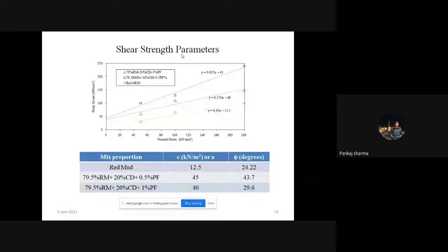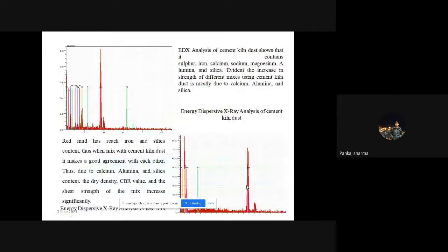and pure red mud, and it is clear from the table that for the pure red mud, the cohesion value was recorded 12.5 and the phi value was 24.22. For the mix with 0.5% fiber, C value increases up to 45 and phi value increases up to 43.7. With further addition of fiber up to 1%, the C value and phi value also start decreasing, as clear from the table value. Also, we have conducted the EDX test for the different mix, different waste product.